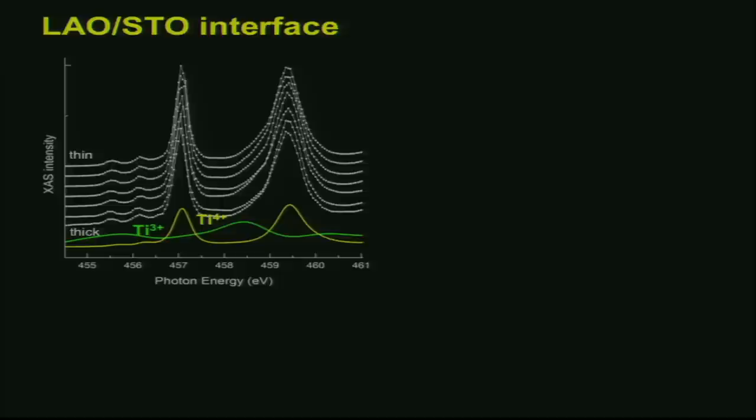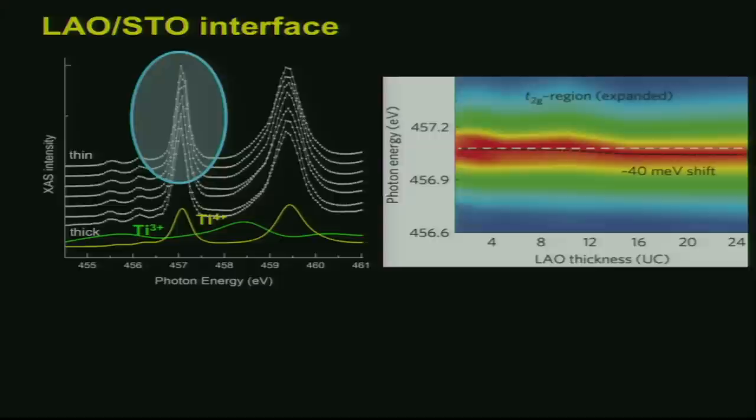However, if you make a very thin LAO sample, your X-ray penetration depth is much deeper, so you can get the whole signal from the middle of the STO bottom. So it's kind of messy, but we may focus on only this part. If you see that, the spectra change. They move to the low binding energy side when you increase the thickness. As I said, increasing thickness means you can see the interfacial sensitive signal. So this means the interfacial signal moves to the low binding energy side.